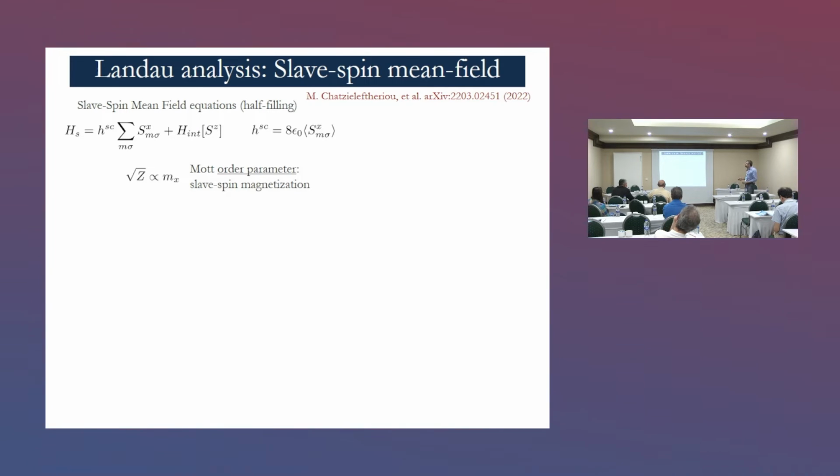and in which the Mott transition is pictured, I mean, the system is described with quasi-particles, of which the renormalizations are calculated through an auxiliary system of spins on a lattice. And the Mott transition is mapped into a ferromagnetic to paramagnetic transition as a function of the interaction strength.